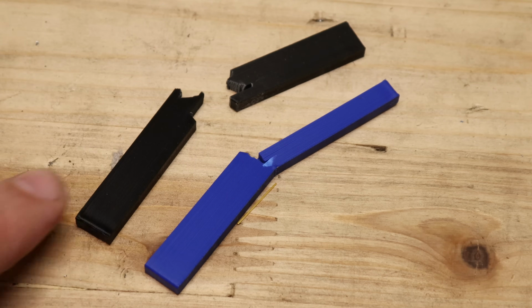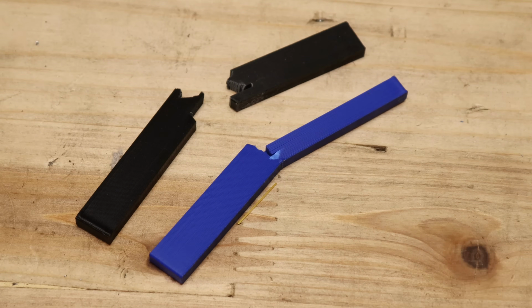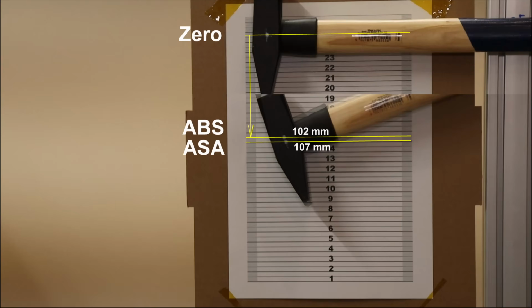Strange break of this ABS part, and this ASA broke only when the hammer swung back. These are the edge positions of the hammer. The difference is not big. The ABS is slightly more brittle compared to the ASA, but both materials are just a little bit above the average ABS toughness.